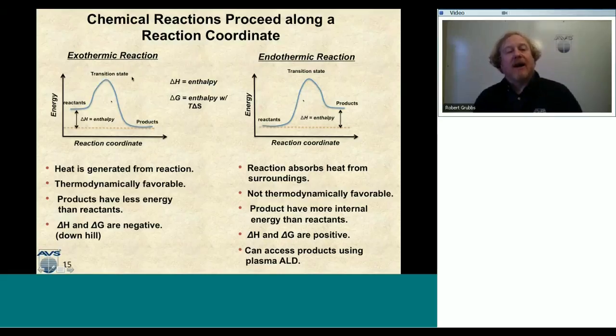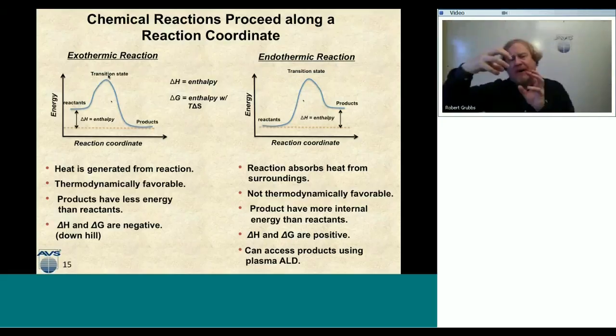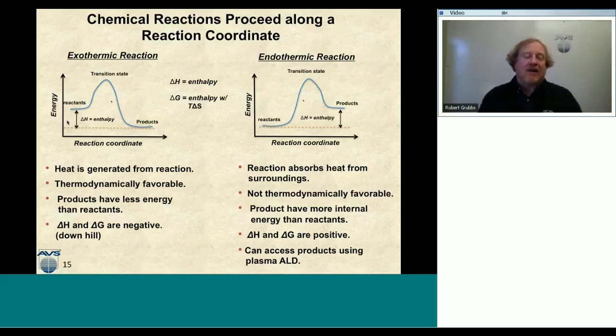in order to get from reactants to products, you have to go through this transition state. So this transition state is a state that's slightly between the reactants and slightly between the products. So we will have reactants coming in, and they'll both be bonded simultaneously, and some can fall back to the reactant state, and some can fall back down to the product state. So what we see here is that the difference between reactants and products is called the enthalpy, and if the enthalpy is negative, then I know that the reaction is downhill. I've also thrown in there delta G. Delta G and delta H are, let's say, proportional to one another. It's just that the delta G term takes into consideration the entropy of the reaction. So if the products are more entropic than the reactants, like if the products are going out into the gas phase, then there's a little extra kick for the reaction to take place because I'm going to more entropy, and that's what the delta G term is.